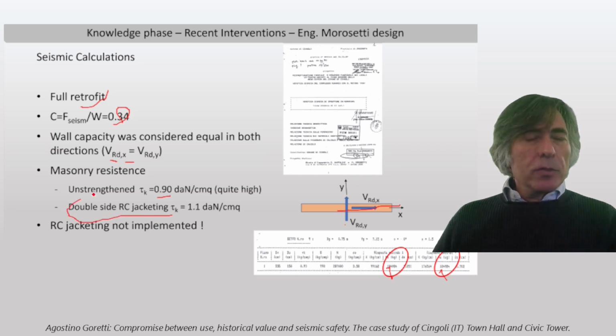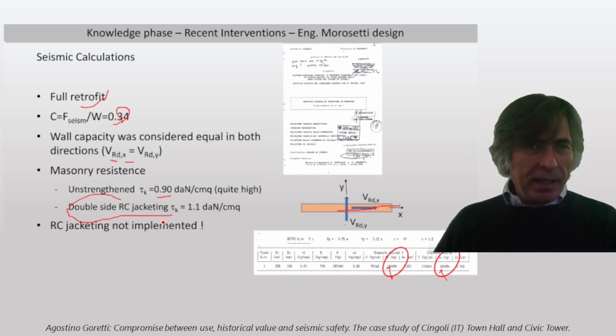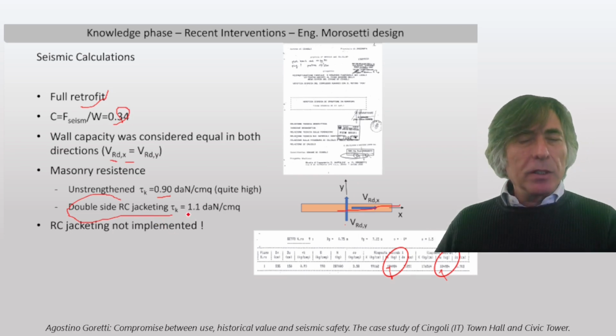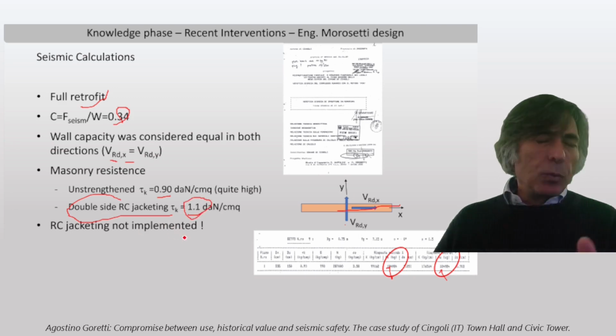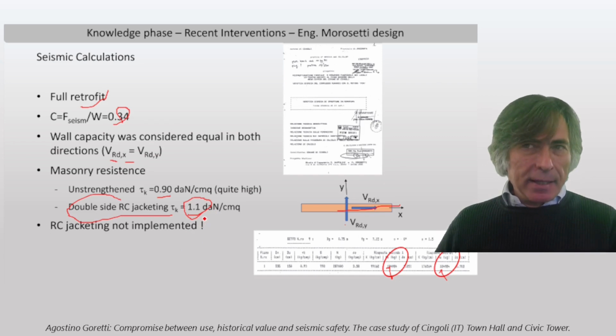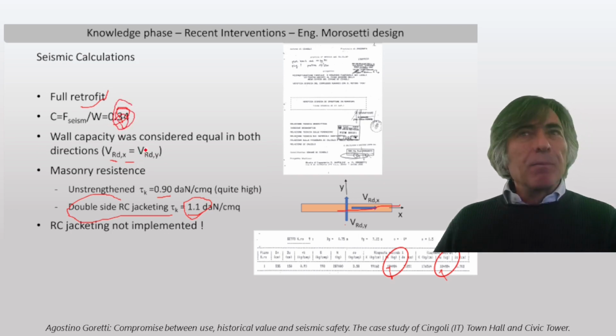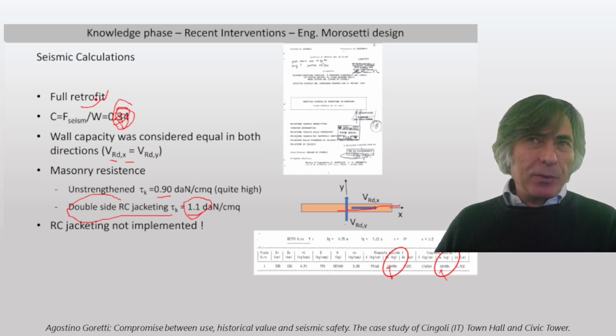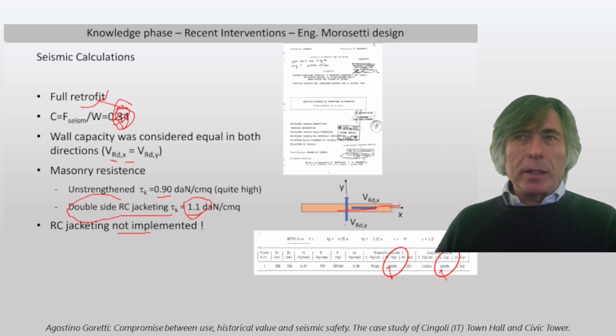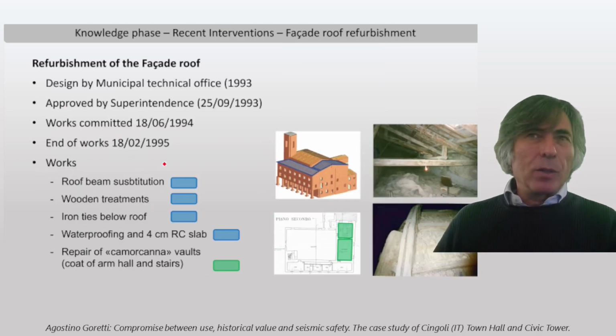In the calculation, double side reinforced jacketing of each wall was considered, so quite different from the remove and replace intervention. And the resistance adopted is quite acceptable for that type of intervention. Not all the walls in the building had some type of intervention. So it's due to all these reasons. The result of this 34% shear capacity and full retrofit is, in my opinion, especially questionable because the reinforced concrete jacketing has not been implemented at all. So full retrofitting of this building is quite questionable.